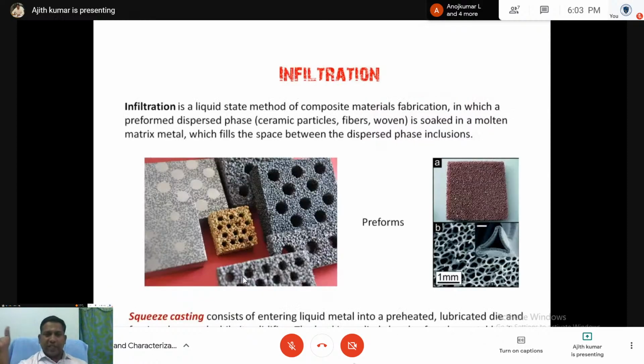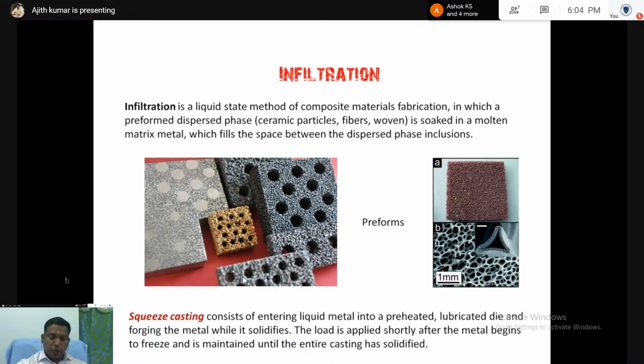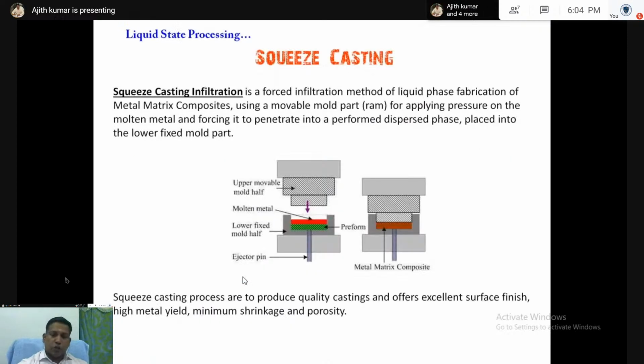And the second one is infiltration. This is the infiltration method. For the infiltration method, we have a ceramic preform. On the ceramic preform, we pour the liquid metal, and using a press, all the liquid metal will infiltrate into the ceramic preform, then we can get the composite. Among the infiltration methods, there is squeeze casting. This is a squeeze infiltration. The green color is the preform, the red color is the molten metal. Then we press the liquid metal. During that pressing, infiltration will happen.